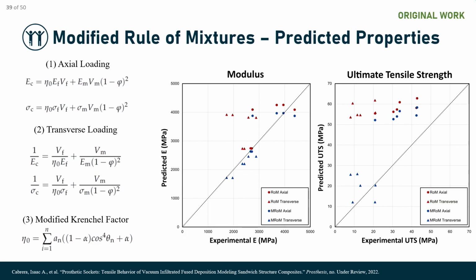1 minus phi squared is actually quite a common one. It's the correction for porosity. We could see in those images that there was quite a bit of porosity. In the Gibson and Ashby book on cellular solids, they describe different corrections for different configurations of cellular solids. However, since our materials are very, very dense, they behave more as continuous solids. And so 1 minus phi squared is essentially a very common metric of incorporating porosity.